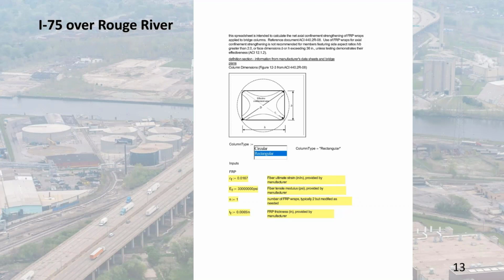The other big difference is that AASHTO specifies a fixed strength reduction factor of 0.85, which is quite restrictive, considering that the entire guide specification really limits the use of these on flexural members, which have relatively ductile types of failures. Whereas ACI 440 follows the general provisions of ACI 318, which allows different strength reduction factors for a tension-controlled failure, which in this case would be a 0.9 strength reduction factor. And if we had a compression-controlled failure, we could use 0.65. So overall, we thought that the ACI specification offered much more flexibility for us.